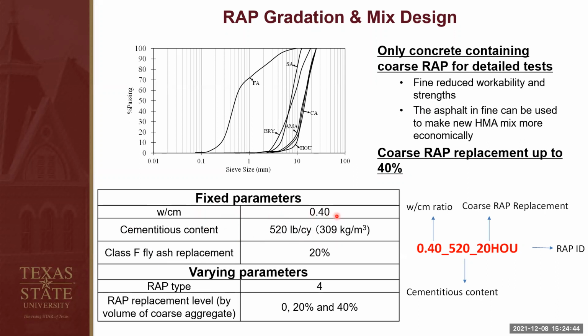We use 0.4 water to cementitious ratio. We use 520 pounds per cubic yard cementitious material content. And then we also use 20% fly ash to replace the cement on a mass basis. And we tested 4 RAPs. We use the RAP to replace coarse aggregate at 20 and 40% respectively for different RAP types.